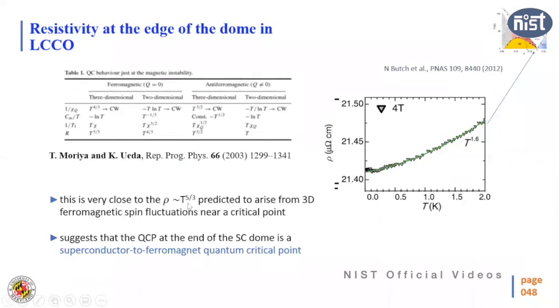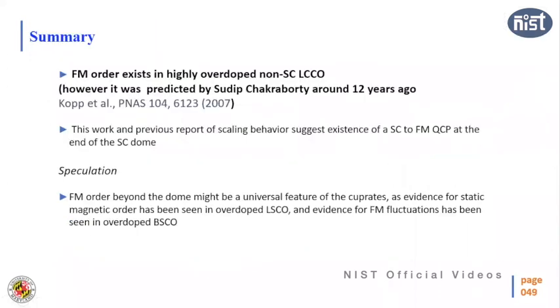And that is what we see, because 1.6 means 5 by 3. 5 by 3 is the behavior from the theoretical calculation, and the experimental observation was 1.6. It's very close to 5 by 3. So all this suggests that there is a ferromagnetism and quantum critical point at the end of the dome.